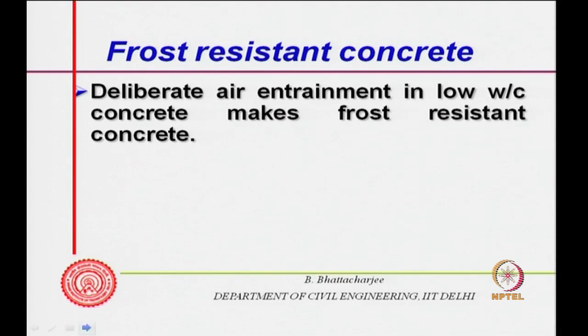So, therefore, for frost resistant concrete, one way is to keep it dry, but that may not be possible all the time. But there was another issue he mentioned: if there are empty pore spaces not filled with water, water can enter during freezing to relieve the hydraulic pressure. That would extend the number of cycles of freezing and thawing, and the durability of the concrete would increase. In other words, the frost resistance of the concrete will increase.